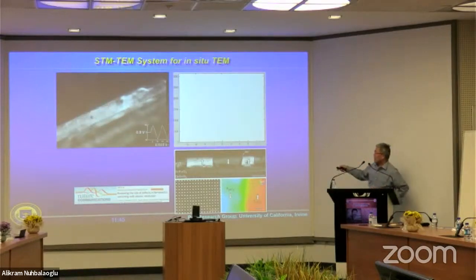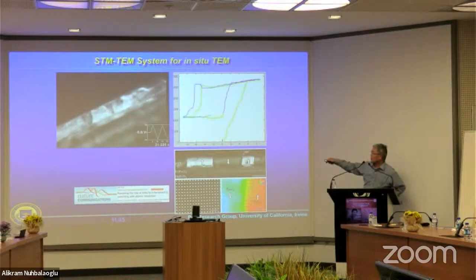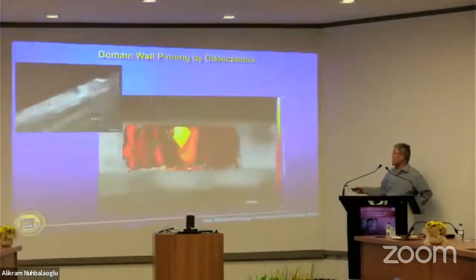Okay, by checking the volume of the new domain switched, you can see the ferroelectric hysteresis loop can be obtained with the integrated video here. And then with atomic resolution imaging, you can determine polarization, and you can see which domains are nucleating. And most importantly, when the domain nucleates here and the dark region starts to extend, that means the domain wall is moving, and we can track it. There's a dark point here, that is a dislocation. You can see how the dislocation affects the motion of the domain wall. That can be explained here.